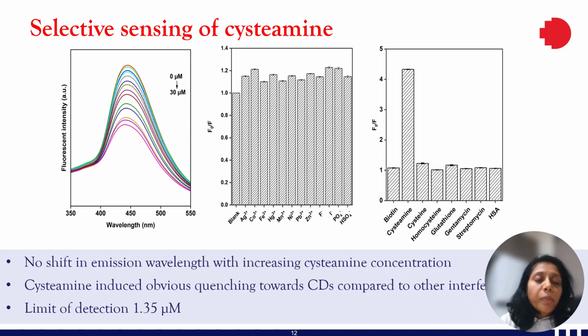The inherent fluorescent property of these as-prepared glutamic acid and tryptophan carbon dots was used for the quantitative detection of cysteamine. As we can see here, there was no shift in the emission wavelength observed, but the emission intensity was found to decrease with the increasing cysteamine concentration. And the limit of detection and limit of quantification were found to be 1.35 micromolar and 4.5 micromolar.